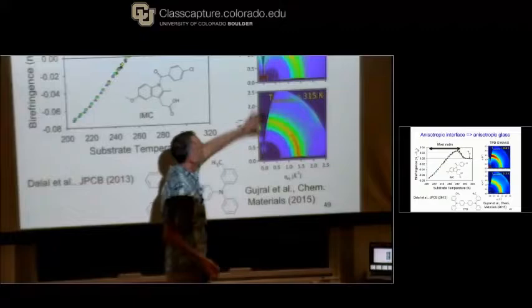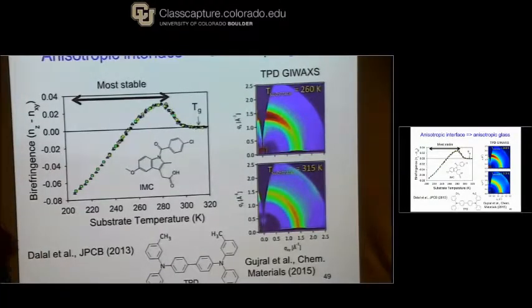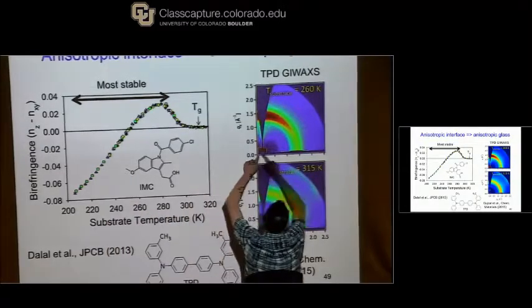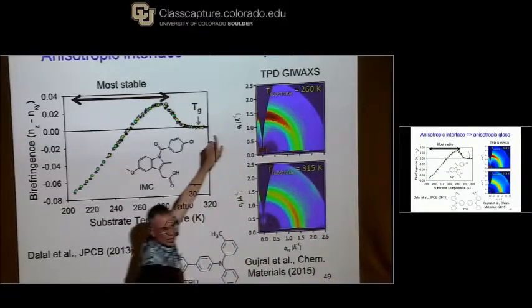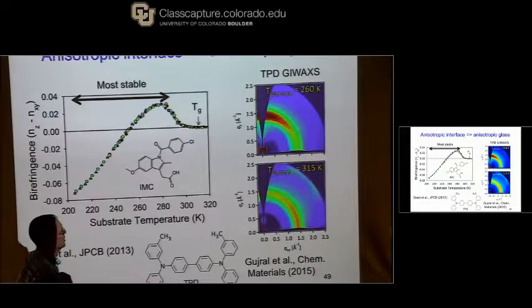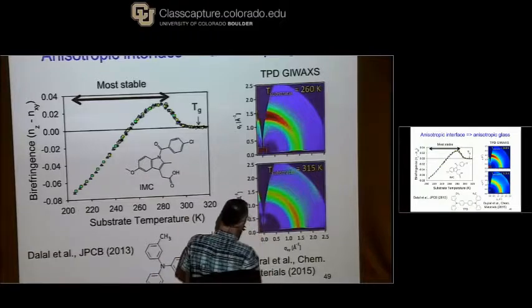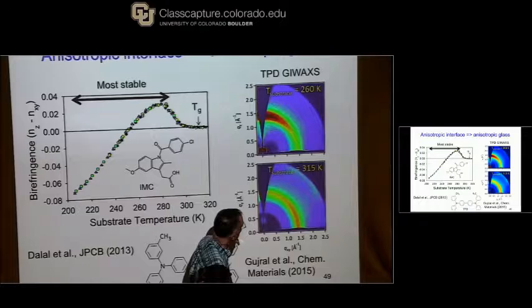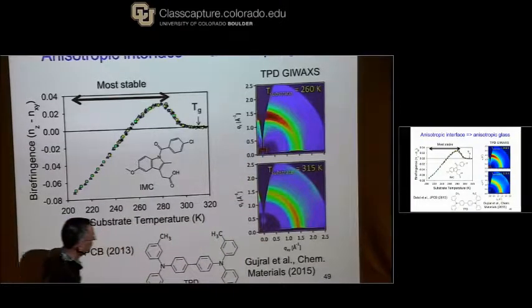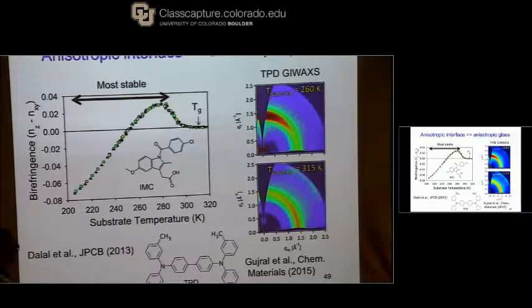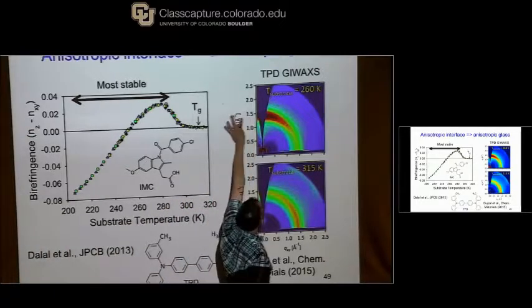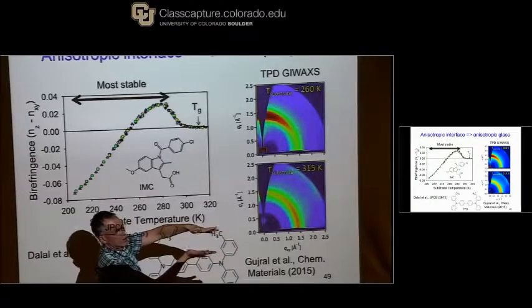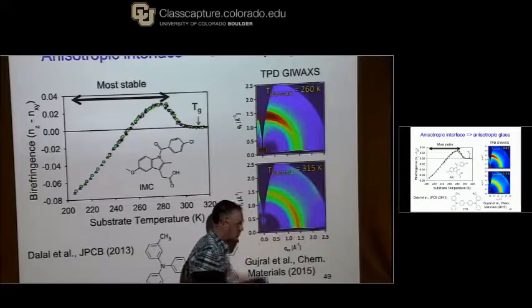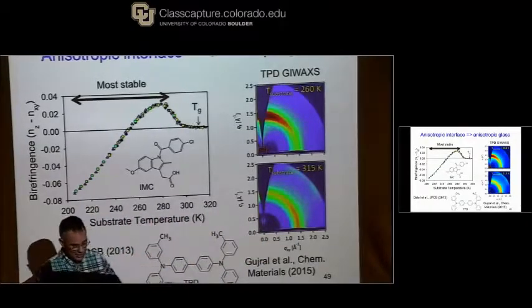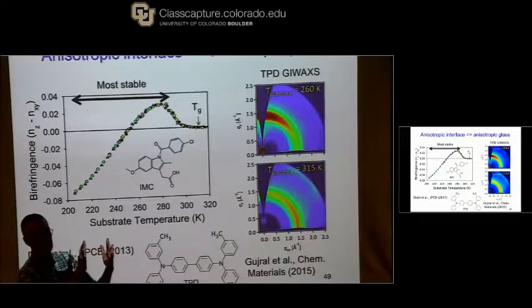So maybe the details about how we do the experiment aren't so important, but it's a two-dimensional X-ray experiment, and so I can tell you that this is scattering in the plane of the sample, and this is scattering out of the plane of the sample. Okay? So the other thing I can tell you is that if you do this for an isotropic sample, then any cut you take along here looks identical. All right? And so this sample is clearly quite anisotropic because scattering is bunched up into the out-of-plane region. And in fact, from this distance here, I can tell there's a tendency for the molecules to line up like this in that film. This film shows the opposite behavior. And because that peak is brighter in plane, I can tell there's some small tendency for the molecules to do this more than they would at random. Okay? Because otherwise I would see an isotropic scattering pattern.